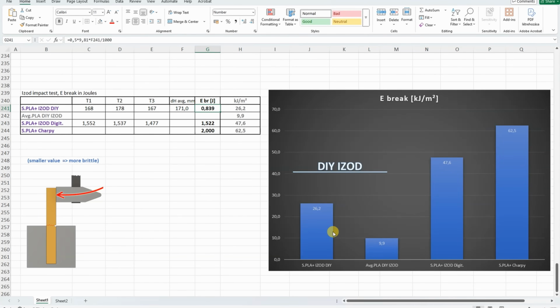It is quite obvious that this Super PLA Plus is much tougher compared to the average PLA. This is the result from my DIY tester. And interesting, with tougher materials I have a bigger difference between DIY and this digital impact tester, but never so big so far. And with the Charpy, don't forget, no real break even with the 2 joule hammer. I ordered another one which will be equipped with 4 joules. I have this weight, but it is much easier to change the hammer instead of replacing the weights.